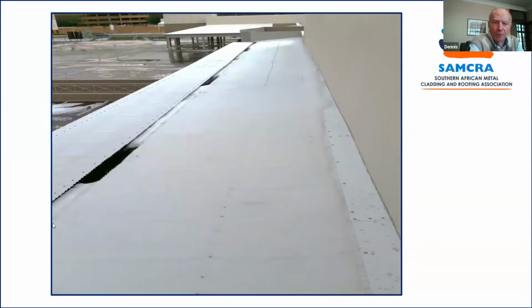Now, when it comes to hail, there are two types of hail. You get large hail, and that is defined as anything bigger than 20 millimeter diameter. And that type of hail does a lot of structural damage, particularly to fragile things like glass panes, weathered translucent sheeting, and that. But the main thing is they normally are fairly short duration, and if they do accumulate in the gutter, because of their size, it's like a bunch of grapes, and there are a lot of cavities between them, which allows drainage to take place.